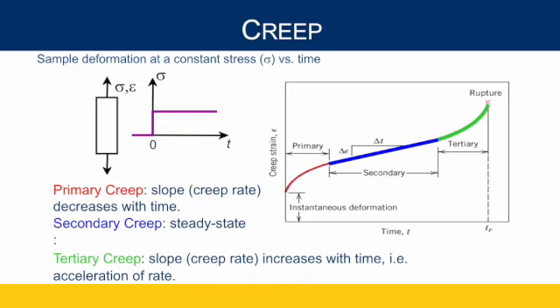So it stretches out. It has a strain that moves over time. Obviously if we do this pretty dynamically, the material will rebound, but if I do it for a long time, the material will deform, the crystals will change, and they'll assume that new shape. Okay, so that's creep. And if you do that for long enough, at a high enough stress, the material will pull apart and can fail.